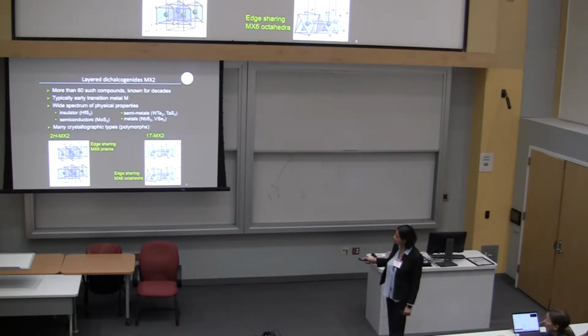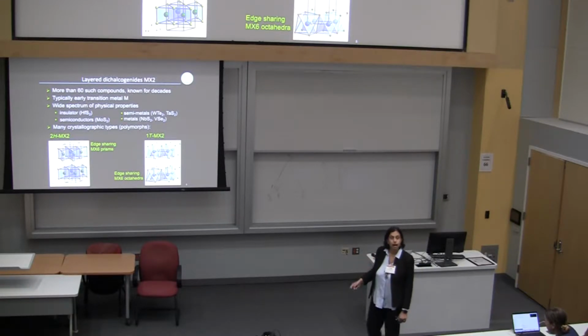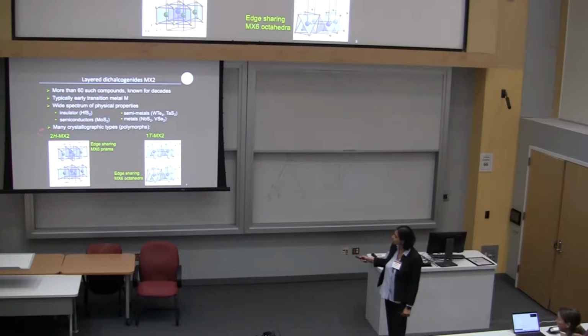So here, for example, in the 2H configuration, these green balls are the transition metals, and the little yellow dots are the chalcogenides. And the difference between this 2H stacking and the 1T stacking is actually in the position of these chalcogenides. So you can see here in the 2H, they're right on top of each other. And in the 1T, the two chalcogenides are not right on top of each other. Okay?